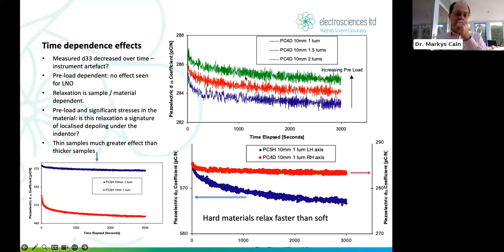And what we're suggesting here is that every time you start this experiment afresh, we are starting the relaxation from fresh again. Okay, in other words, we're starting the aging process again. Remember, we're applying a preload. So it's the preload which is initiating this aging relaxation process. It's much more significant for a soft material compared to a hard material. But what does this tell us?